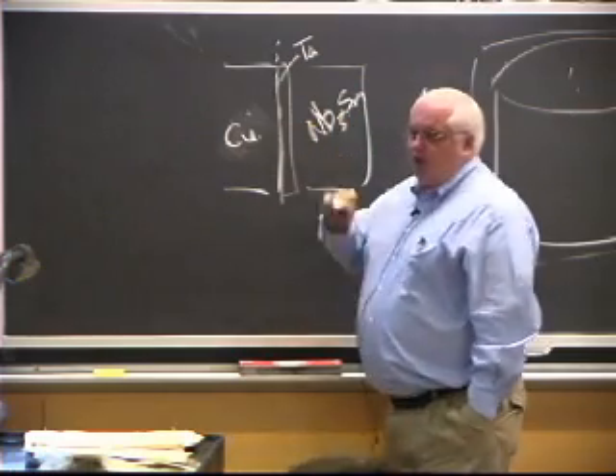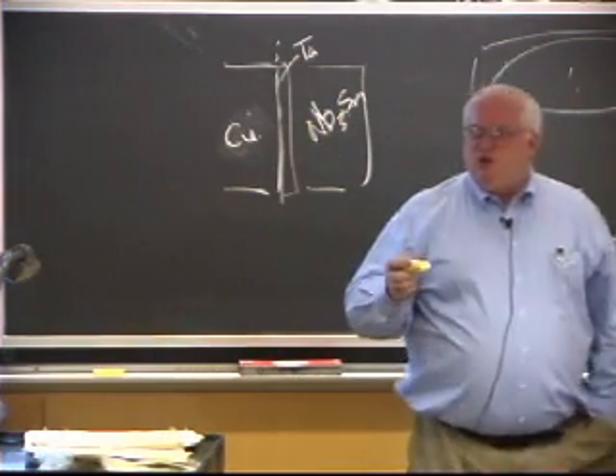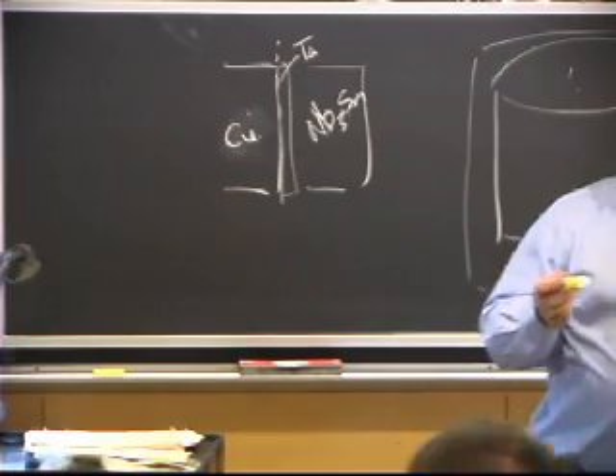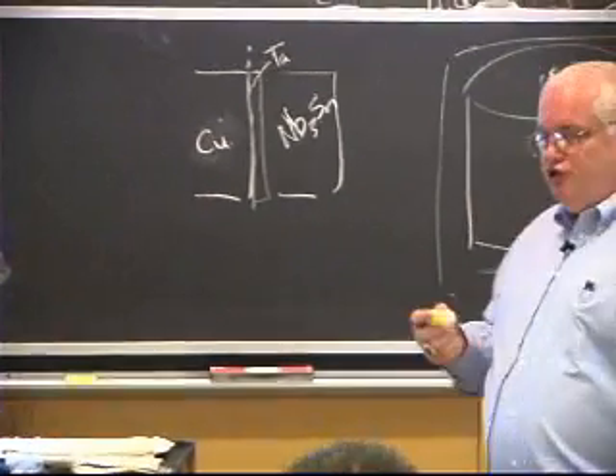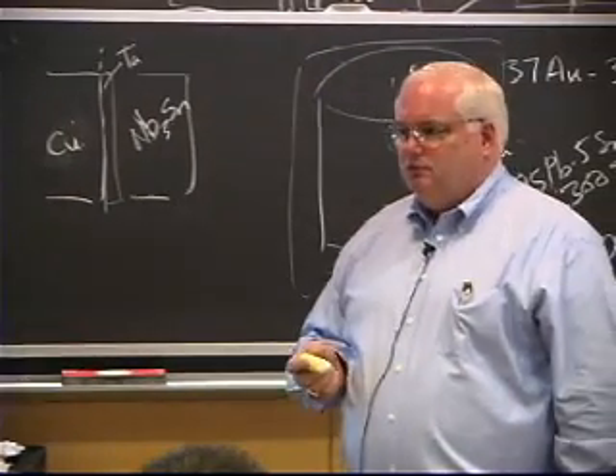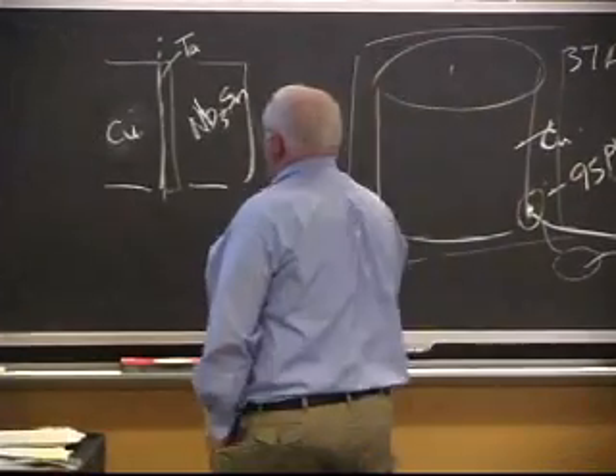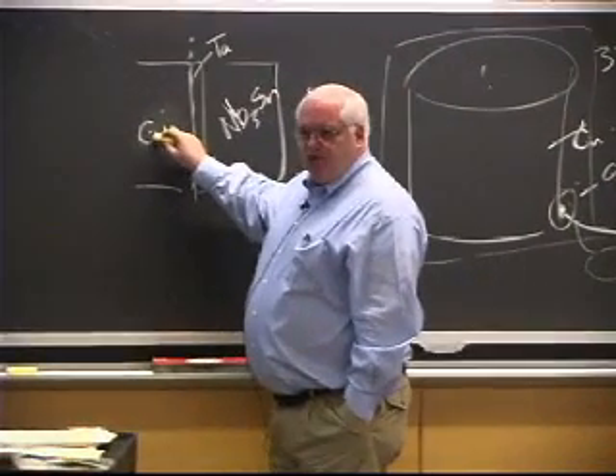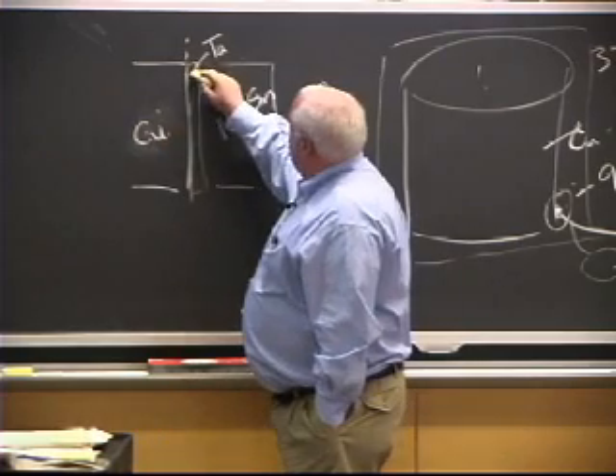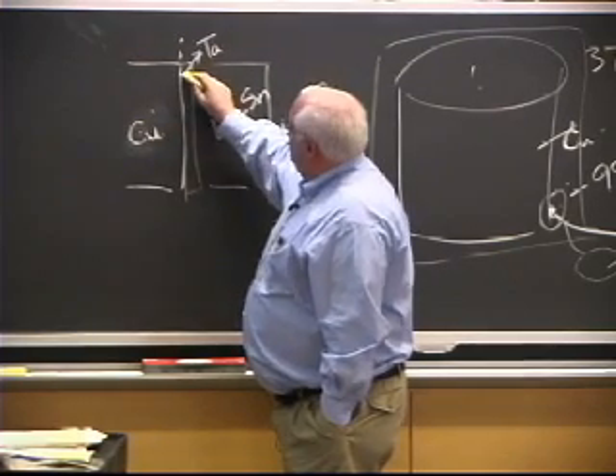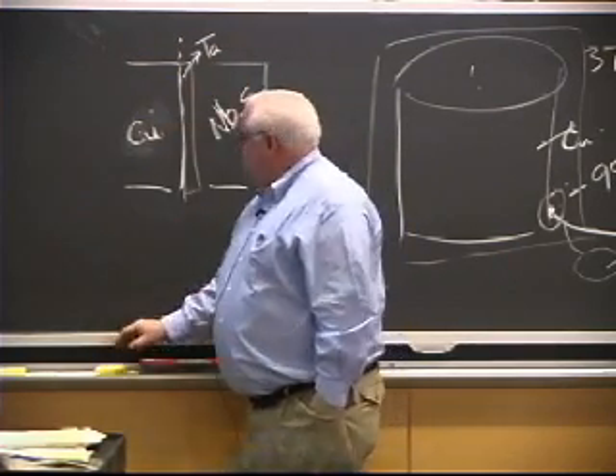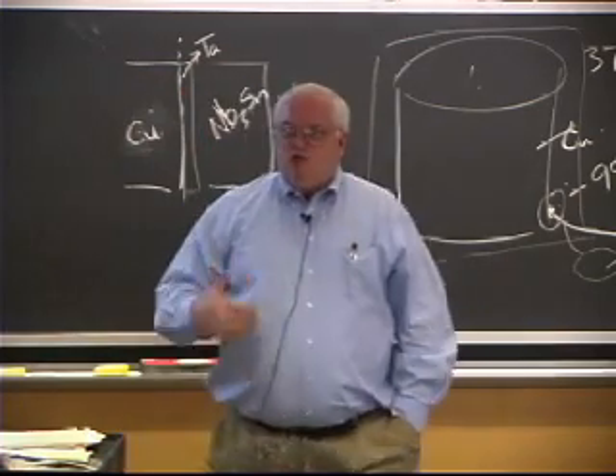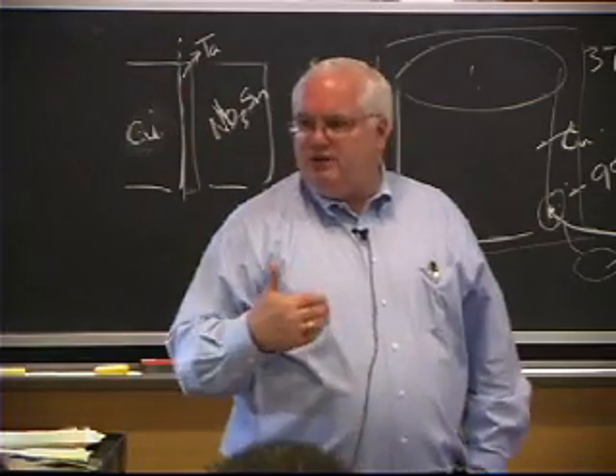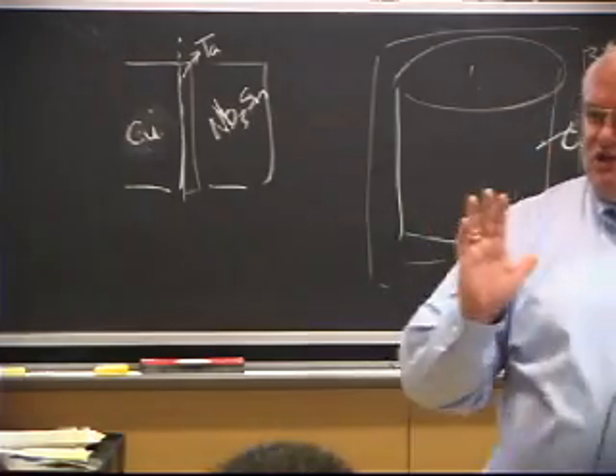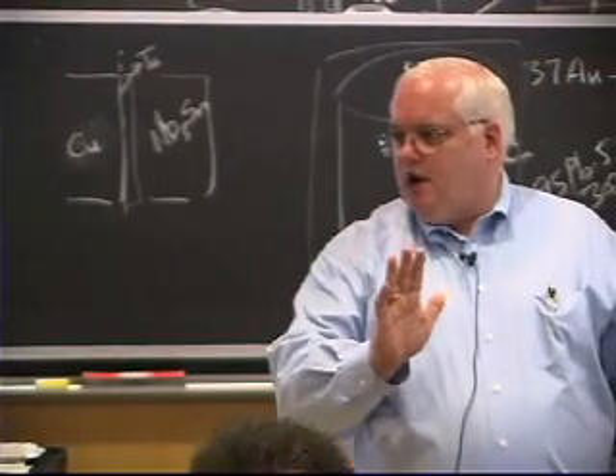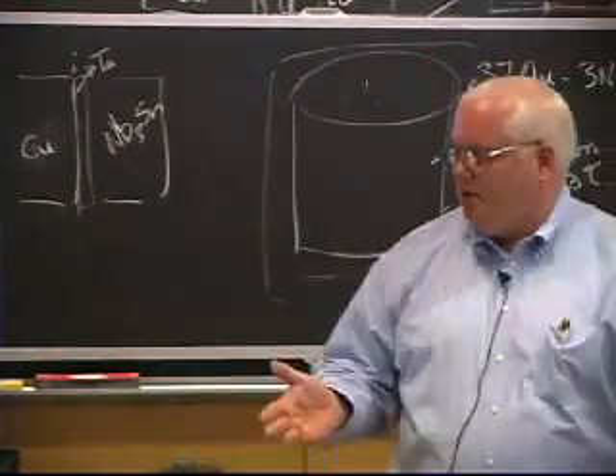And if you put that with the copper, the tin would diffuse into the copper, and you would run into problems because you'd lose your tin and you wouldn't have your superconducting properties. And you can't make this a copper tin alloy because then it loses its good thermal conductivity, which is why you had it here. So what they started doing 30 years ago was, in fact, this was, as my thesis advisor tells it, his idea, they put tantalum in between. And tantalum forms a tantalum-tin intermetallic that stops the diffusion of tin into the copper. So you can put barrier layers in there.